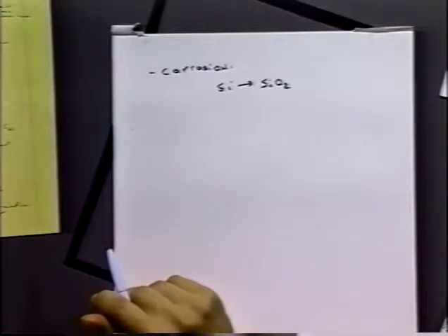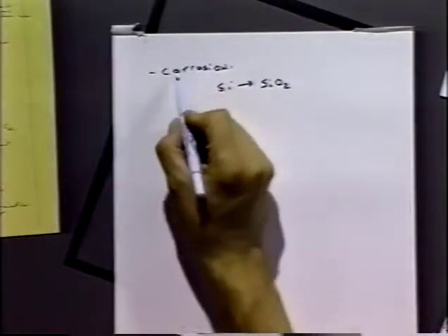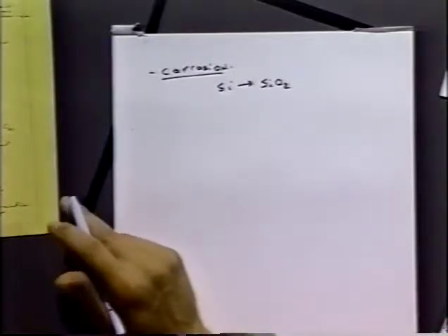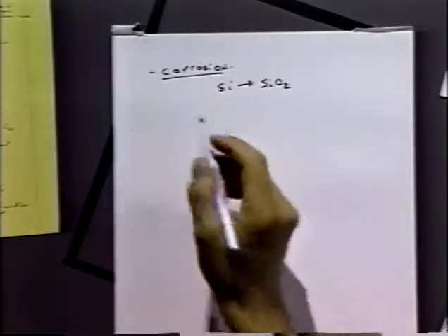Basically, as I already mentioned earlier today, those holes that are present in the silicon material are essentially broken bonds. And so if holes are present on the surface of the silicon, that means that there is a surface exposed broken bond, which now is very reactive for solution species. And so the silicon can essentially corrode away very rapidly in the presence of excess holes on the surface. So what you'd normally get would be silicon oxides from the breakdown of water. So that's a problem with experiments in semiconductors, particularly P-type semiconductors that have an excess of holes.